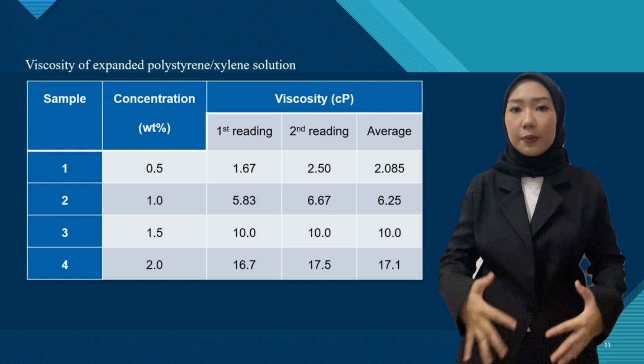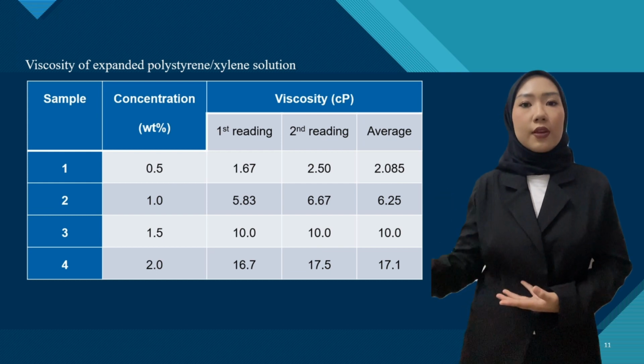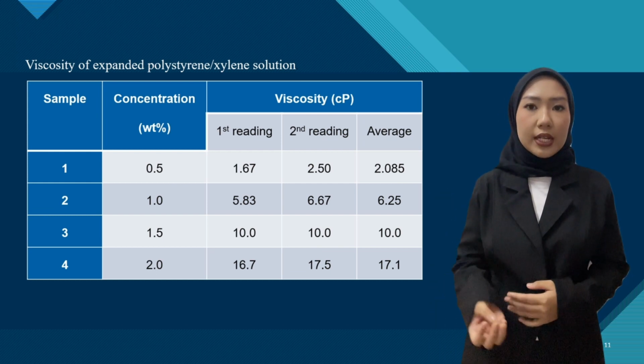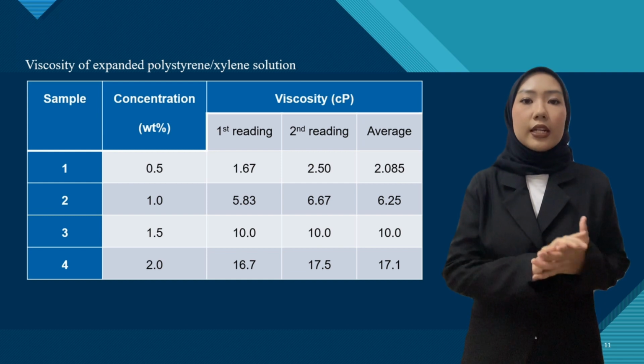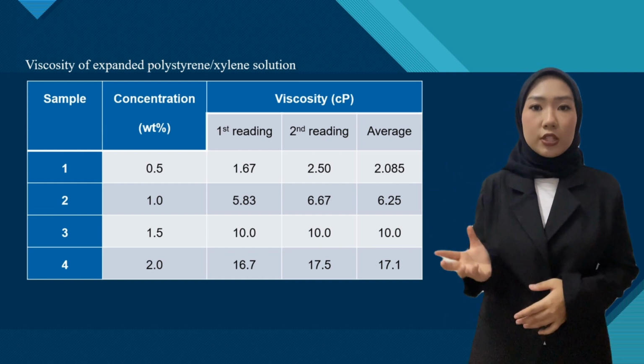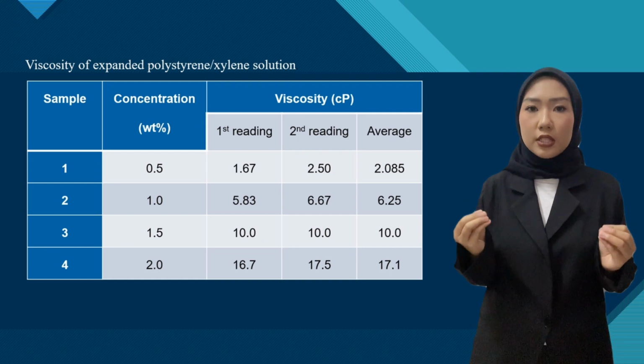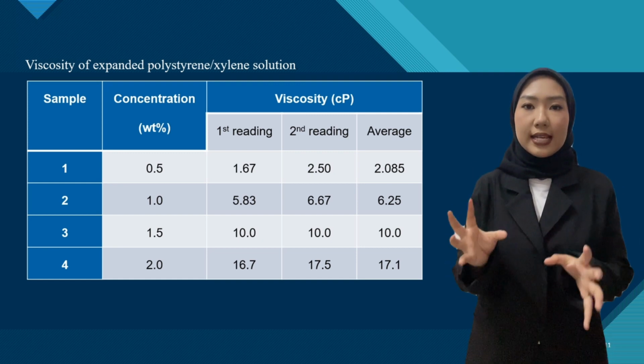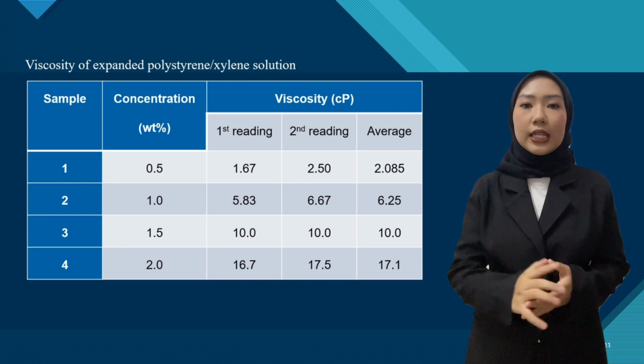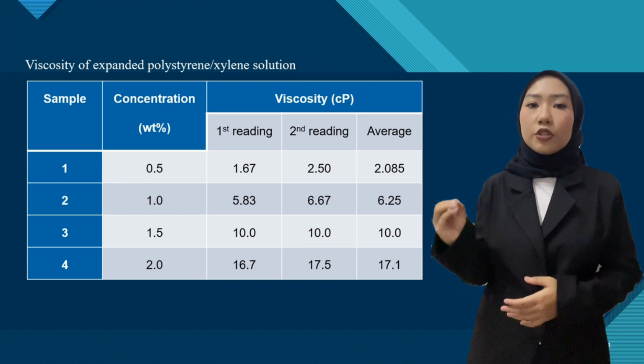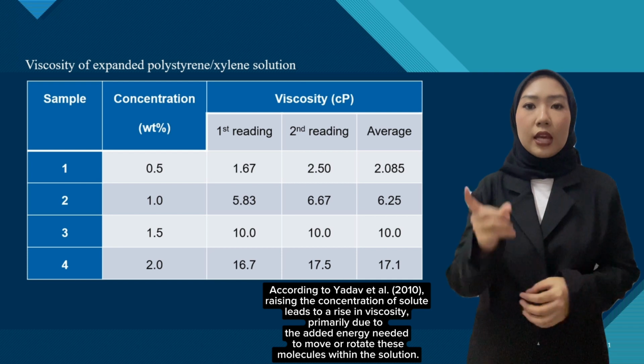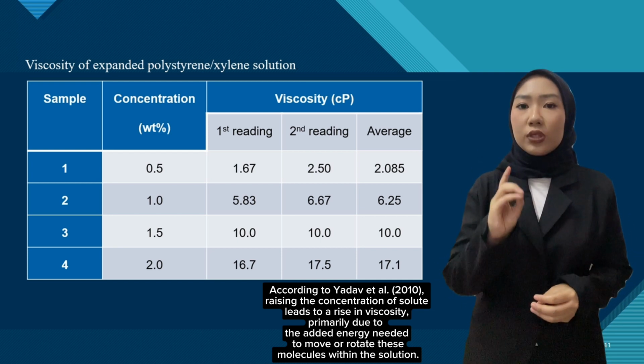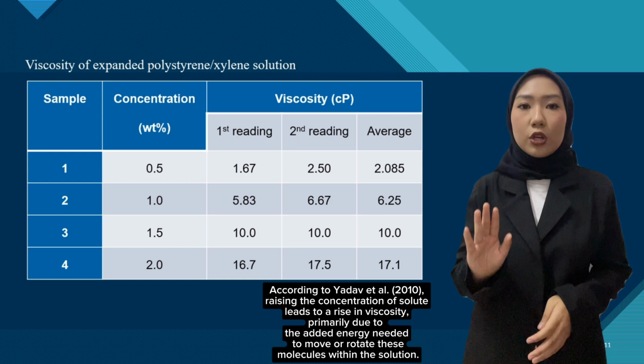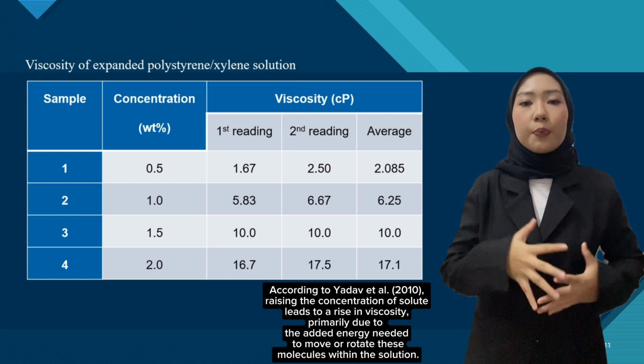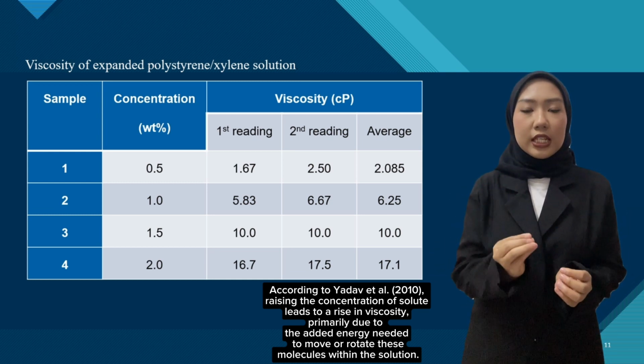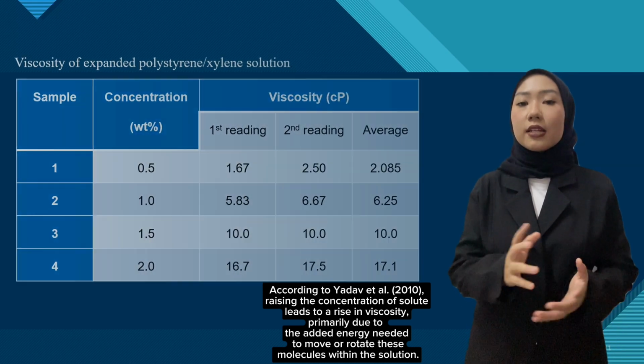Because the process was time-consuming, the material was replaced with different concentrations of expanded polystyrene mixed in xylene solvent. The data from the viscosity test shows the viscosity of solutions of different concentrations of expanded polystyrene with xylene. From the data, the viscosity increases with concentration. This shows that concentration affects viscosity. According to Yadav et al. 2010, raising the concentration of solute leads to a rise in viscosity, primarily due to the added energy needed to move or rotate these molecules within the solution.